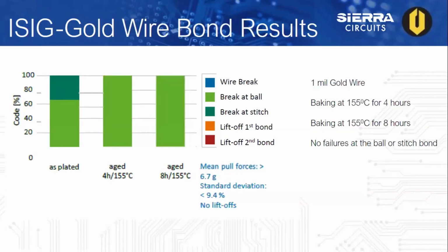Now, gold wire bonding testing was also completed on ISIG. The conditions for this testing was using a 1 mil gold wire, no heat treated samples, a sample baked at 155 degrees Celsius for 4 hours, and then also a sample baked at 155 C for 8 hours.